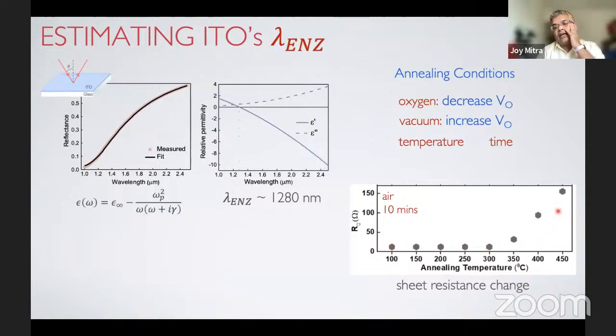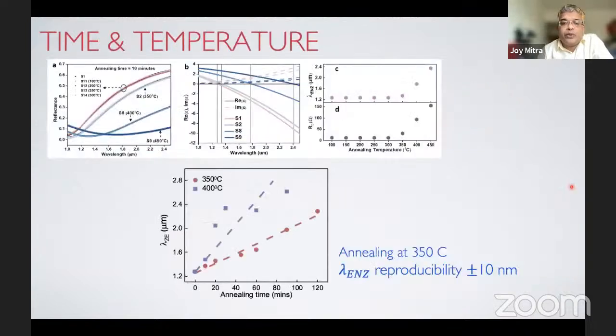Now, since it's a conducting material, we knew that we could easily check whether properties or number density are changing by looking at the resistance of these films. And what we saw was that if we anneal it in air, which is oxygen rich, for typically 10 minutes at various temperatures, beyond 350 to 400 degrees centigrade the film was becoming resistive, showing that most likely the number density was decreasing. So once we realized this, we went ahead and optimized annealing in oxygen as a function of time and temperature. After a few months of detailed work, we figured out that if we do the annealing at 350 degrees centigrade in air, the oxygen vacancies are quenched, the number density decreases, and the film becomes more and more resistive.